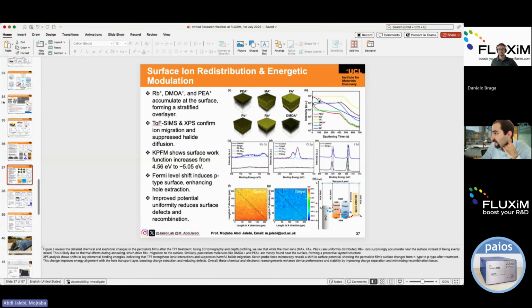As you can see, this is a clear experimental observation that shows rubidium is highly accumulated at the HTL side. We think this might happen due to the heat of the annealing step of the passivation, which can cause rubidium to move from the bottom to the top and help us passivate that surface as well. But it doesn't mean it doesn't exist at the bottom surface. It's just a matter of concentration. It has high concentration at the top, lower concentration at the bottom, and also some concentration in the bulk. It's a kind of linear distribution based on the Fluxim measurement.